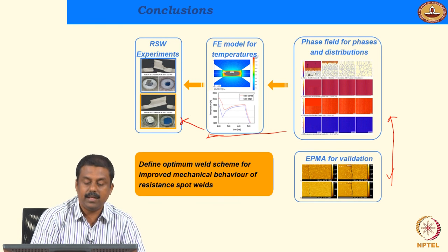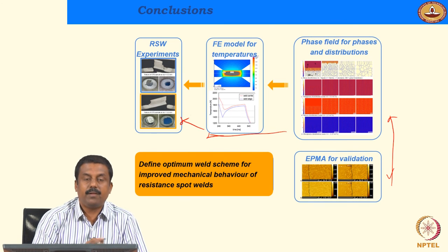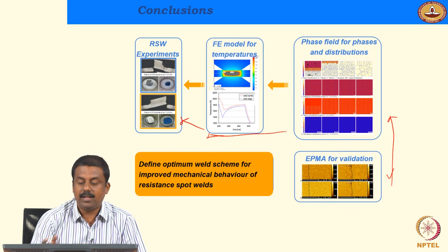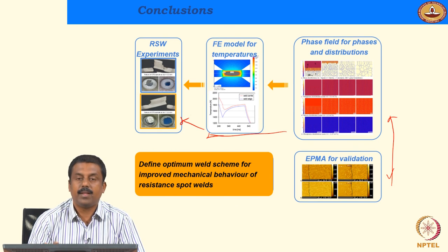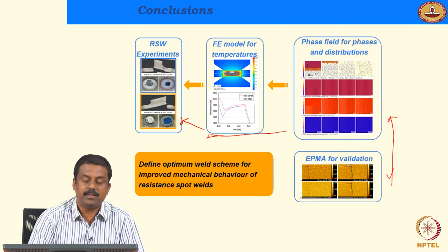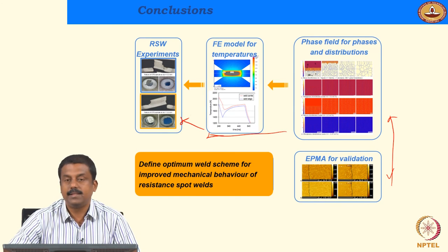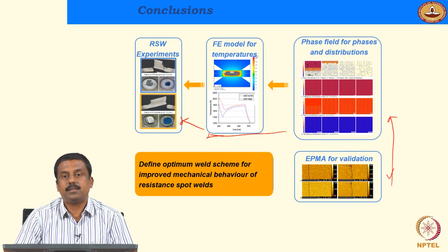to get these microstructures. Ultimately you will have, using that thermal cycle, the best microstructure. So instead of playing around with the welding thermal cycles to get better mechanical properties, you identify the mechanical properties, the microstructure and the elemental segregation behavior which can give you those mechanical properties. Once you know that, we can get the thermal cycles needed to achieve these mechanical properties. So with this we would like to conclude this lecture series. The lesson I want to give you is, it's very important to understand the physics and metallurgy of advanced high strength steels. By understanding the physical metallurgy and the fundamentals of the alloying elements' behavior, the welding thermal cycles can be identified to weld these steels, and we can achieve the best weld from these advanced high strength steels, by carefully understanding the microstructure evolution and the correlation between the weld thermal cycle and the microstructure.